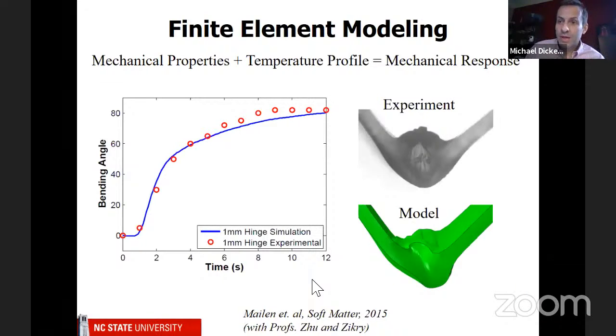And the thing that was really satisfying is if you look at the hinge where this thing is folding, you can see these are the panels and it folds right here. And of course, if it shrinks this way, it's going to get thicker this way. And so this is what we see experimentally. And then in the model, we basically saw the same thing.